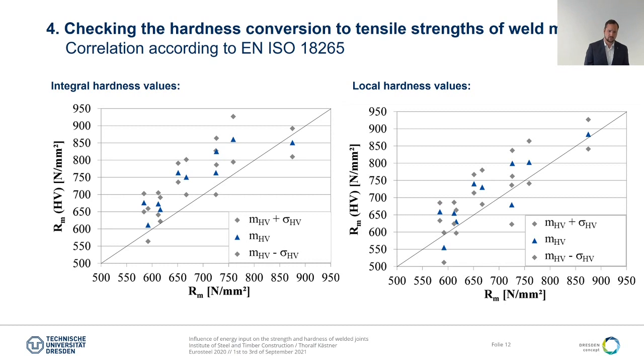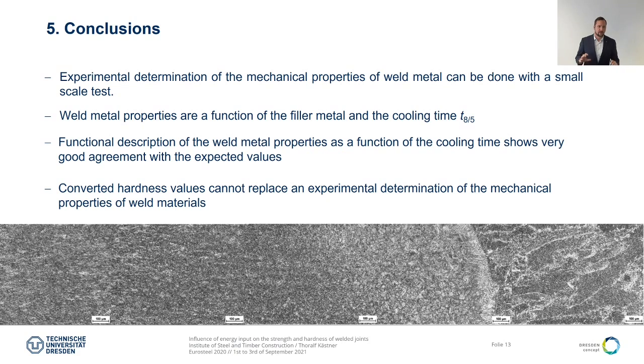Within this code it is also mentioned that you need to take into account a specific standard deviation of about 85 Newton per square millimeter for the test results, and therefore they are usually not useful for our design formulas, because due to this large scattering we get really conservative tensile strengths to use. So therefore the test procedure we developed is a good alternative to determine the mechanical properties of welds in a good way. And this is also one of our main findings.